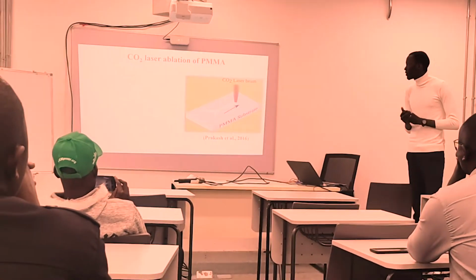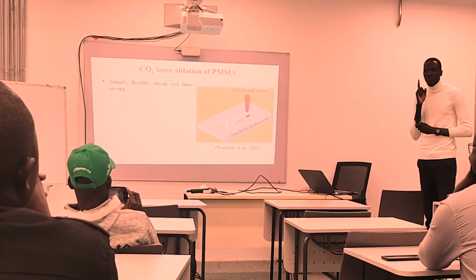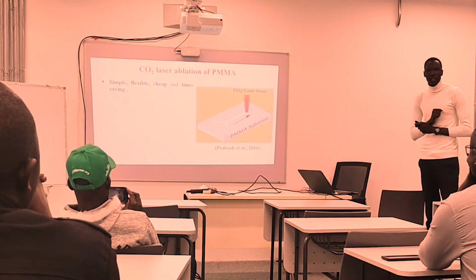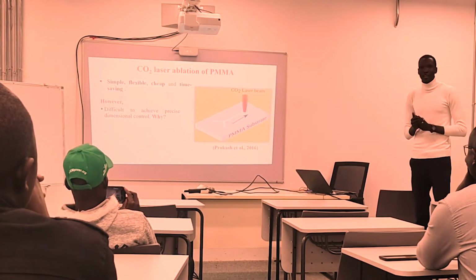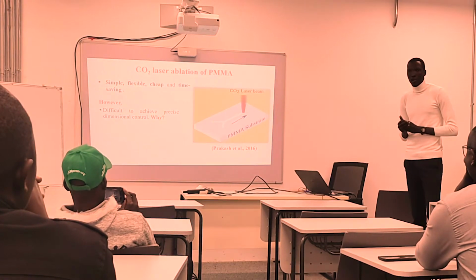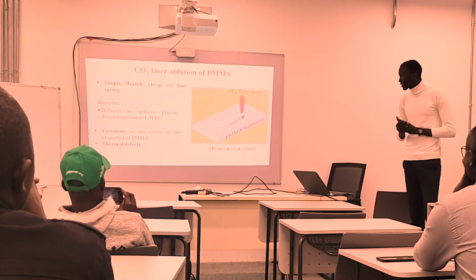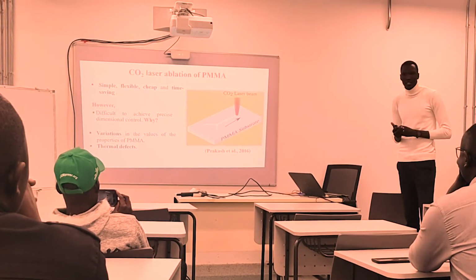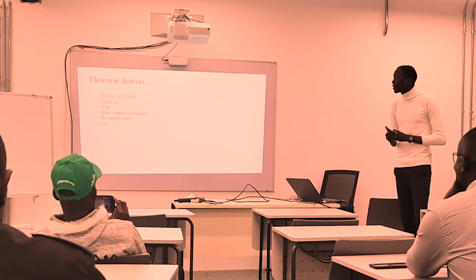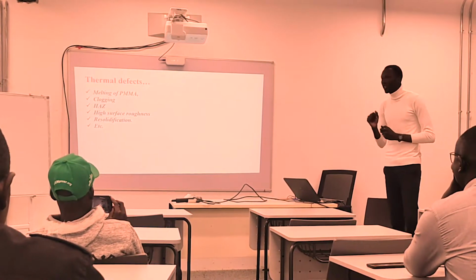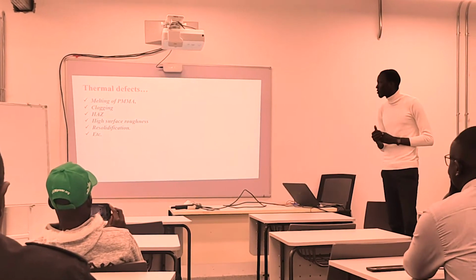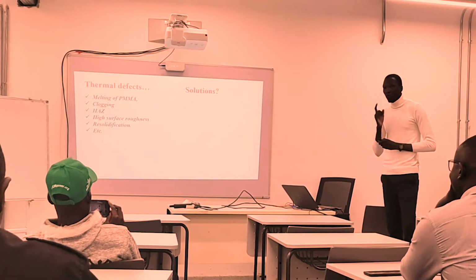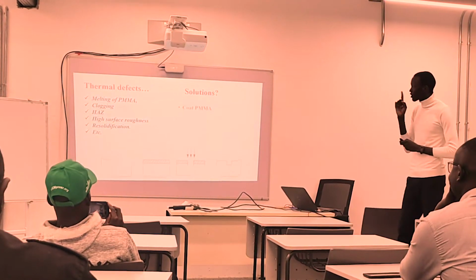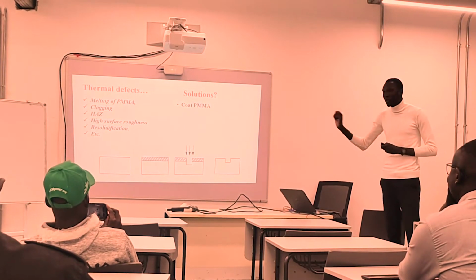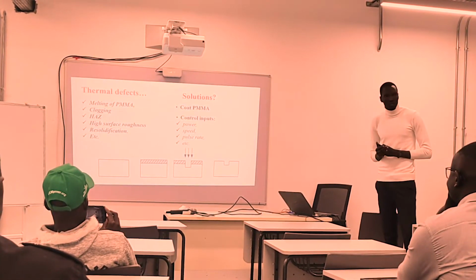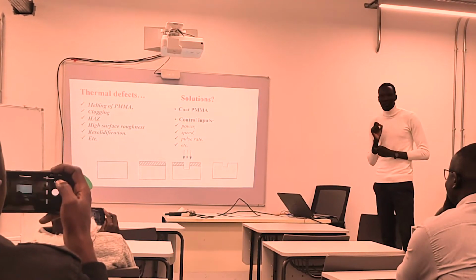Now, CO2 laser ablation of PMMA is simple, flexible, cheap, and time-saving. But it is difficult to achieve precise dimensional control. Why? Because of thermal defects, and also the ignorance of how the properties of the material change under different conditions. The defects include melting of the substrate, clogging, heat-affected zone, high surface roughness, and resolidification in the ablation zone. What are the solutions? The solutions are to coat the material before fabricating the microchannels, and then to control the inputs like power, speed, pulse rate, and others.